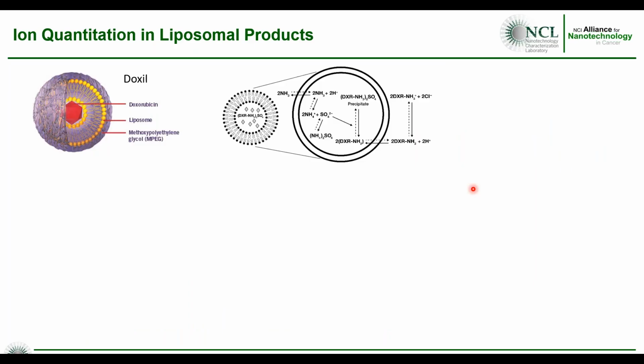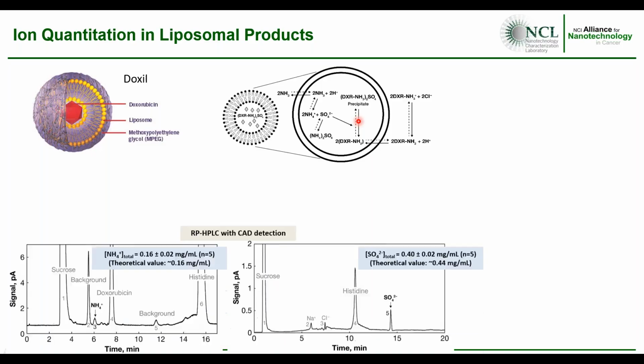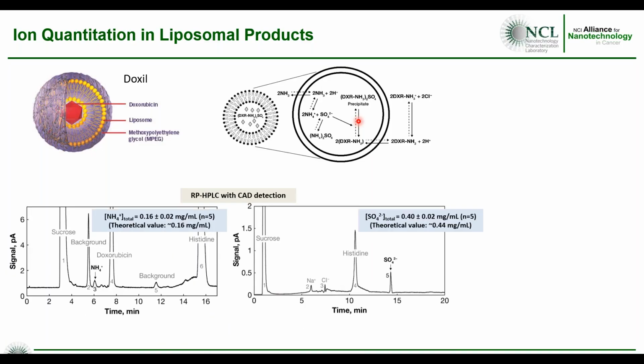The next example is looking at ion quantitation in liposomal products. And for this, I'm using Doxil as an example. So everyone's probably familiar with Doxil. When you load doxorubicin, you actually precipitate it out within the interior as a crystal. And this is what you typically see in a cryo-TEM micrograph of Doxil. So we wanted to quantitate the amount of ammonium and sulfate in the formulation.